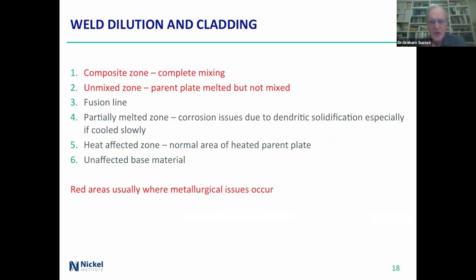Corrosion issues can occur in that zone basically due to dendritic solidification, especially if it's cooled slowly. That will give you differential things, particularly if you've got molybdenum in there, and there are some of the copper nickels that do have moly in them.